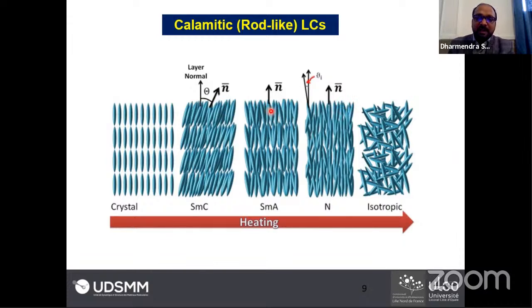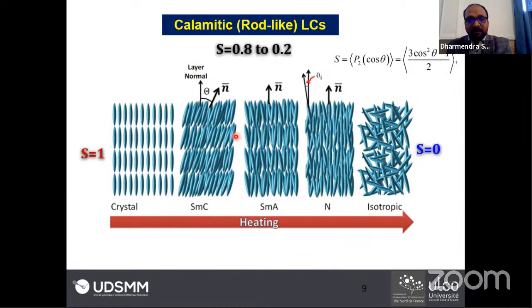So that's why it contains only the orientational order parameter. In the smectics, a layer structure is formed due to the alkyl chains. And this molecular director is parallel to the layer normal in the smectic A phase. That's why it contains the orientational order parameter as well as a weak positional order. But in smectic C, this director is tilted with an angle theta with respect to the layer normal. So this is the tilted phase.